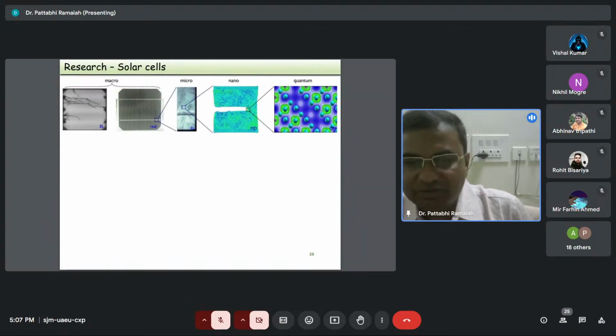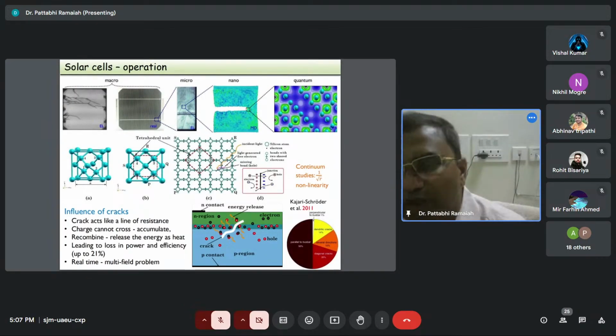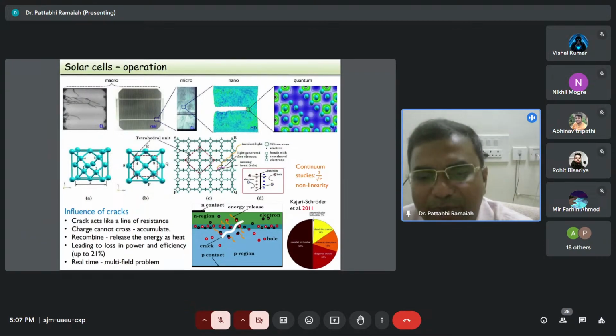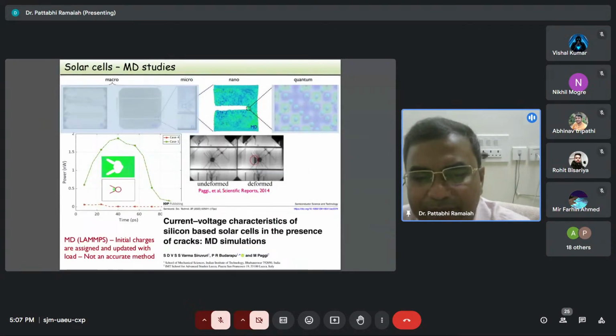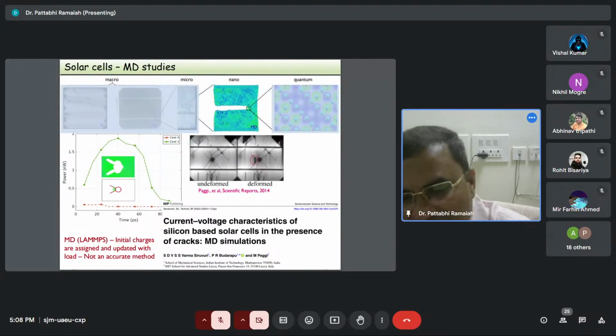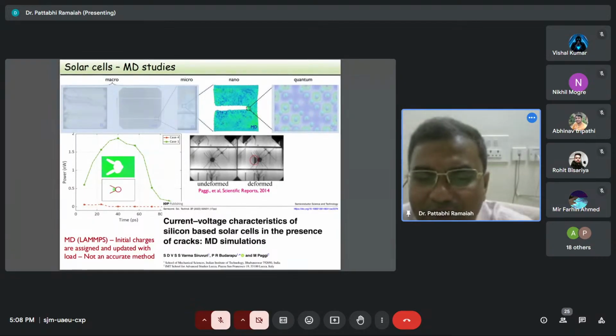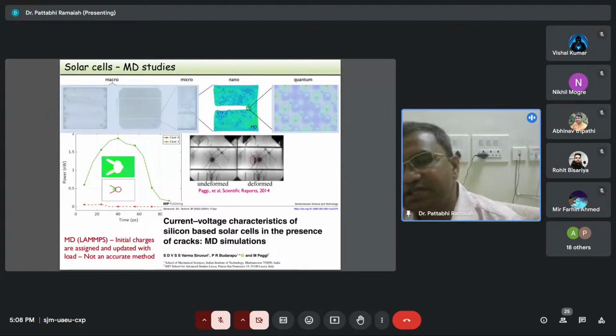So we developed techniques to predict such degradation in power. Okay, so this is the basic mechanics of solar cells. I will skip this because of lack of time. And what I can say is, through our developed methods, we estimated that the power generated from the solar cells in the presence of cracks is significantly lower, almost zero, as compared to the power from other regions of the solar cell. Okay, so this was the main conclusion from our studies.